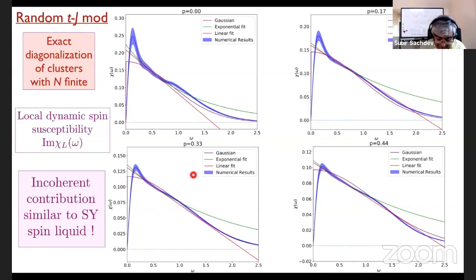It'd be linear in omega this way. So the Fermi liquid would look like this. That's a Fermi liquid. And we do start seeing that at higher doping, but this very sharp, almost discontinuous peak at low doping, followed by the linear in omega dependence, is exactly what SYK physics predicts.